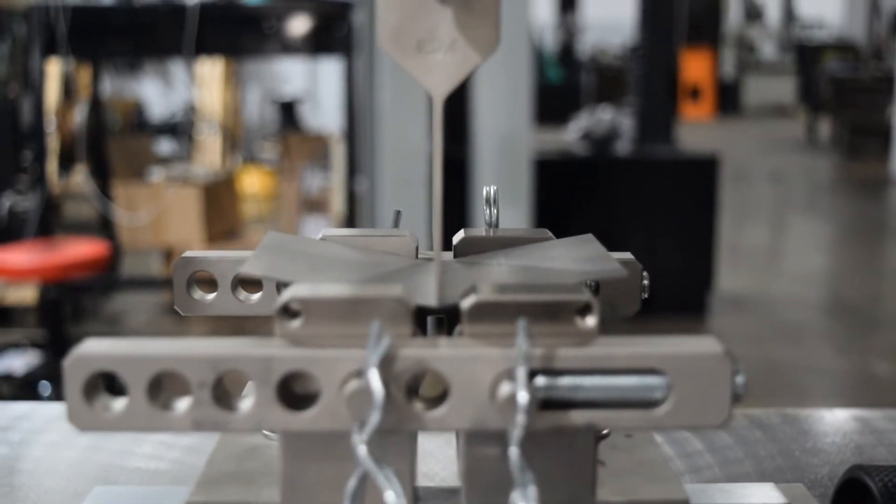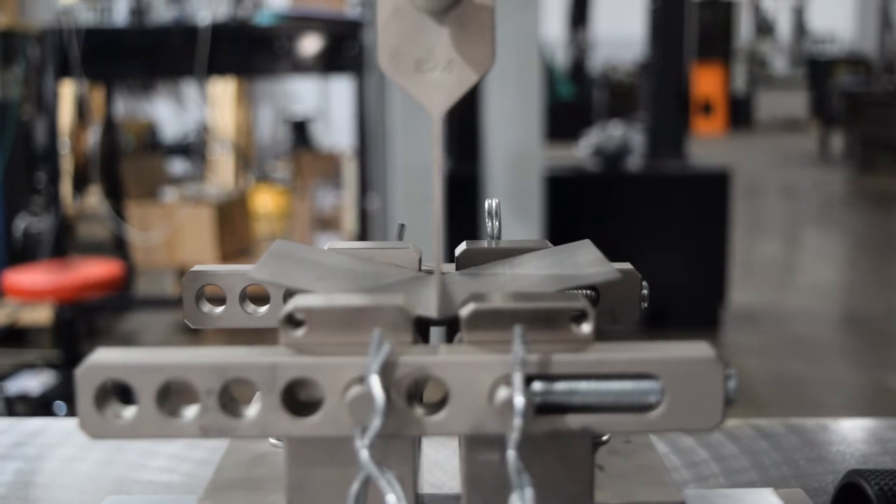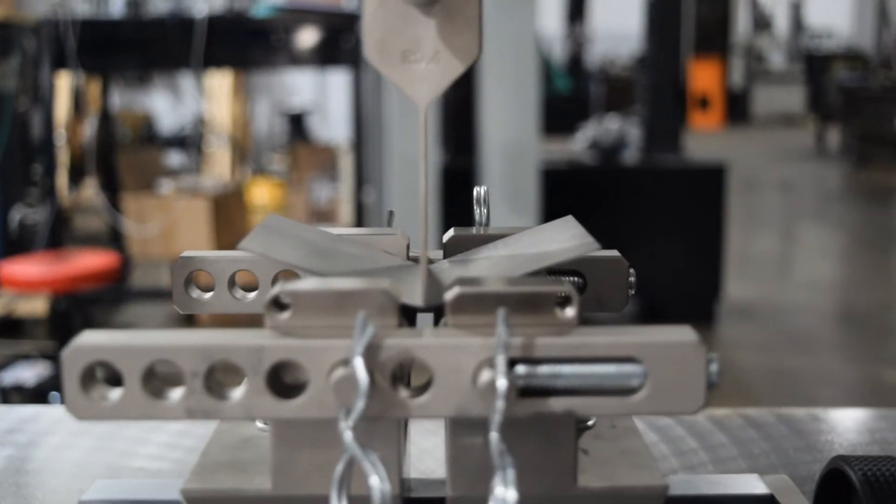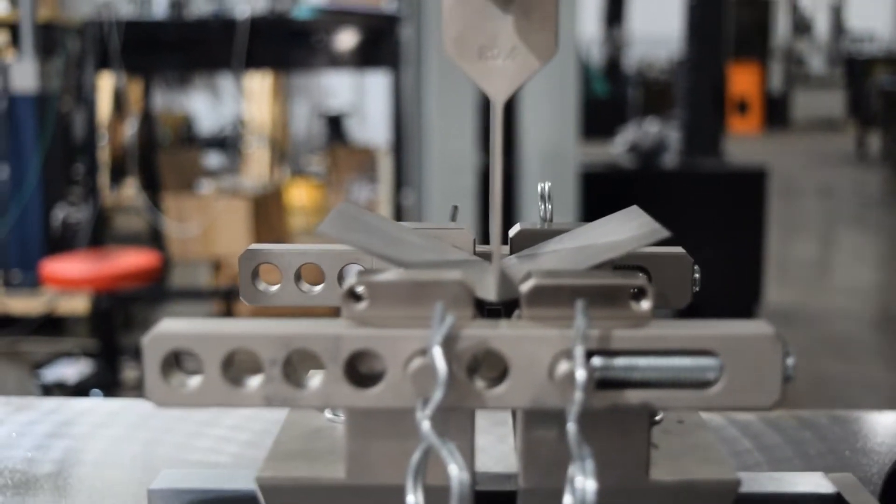As it's going through load, we're moving at 20 millimeters per minute until the specimen sharply increases load or loses load.